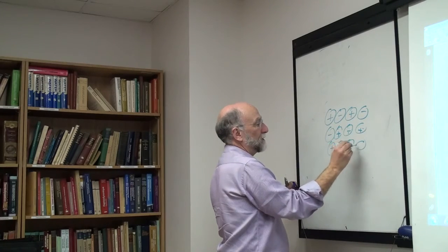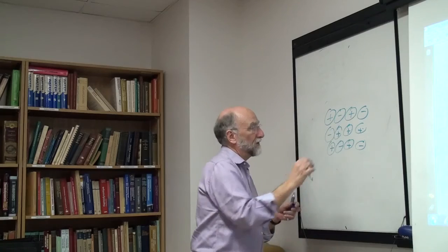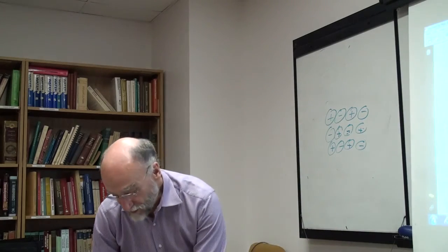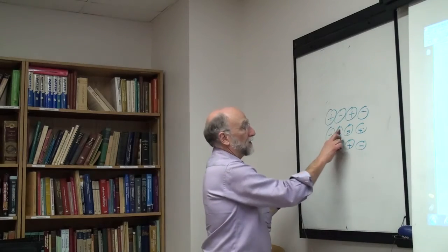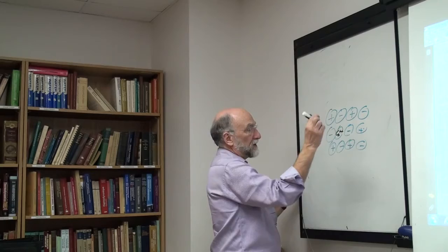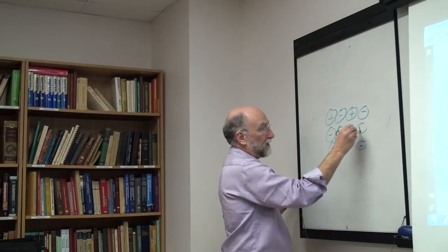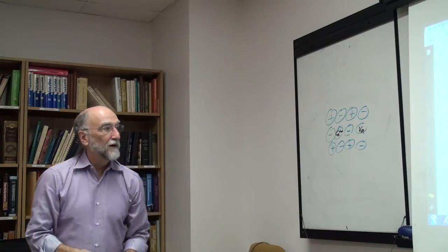So then a calcium is going to go in here, so this will be your calcium. The chlorines stay the same, but we end up with a vacancy. Okay, and the calcium and the vacancy form two independent particles. All right, so now each calcium ion produces one cation vacancy.